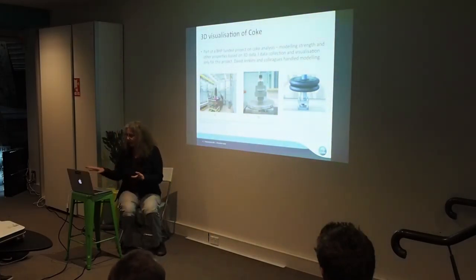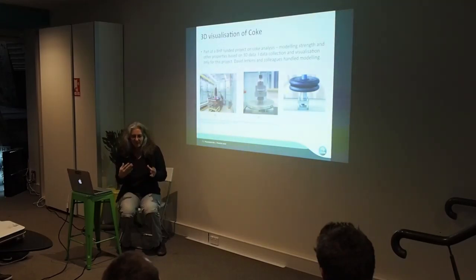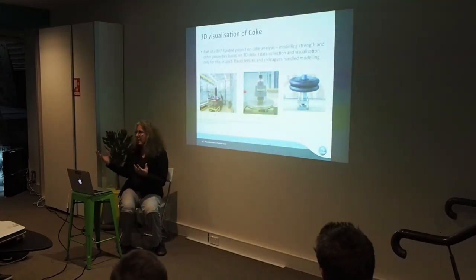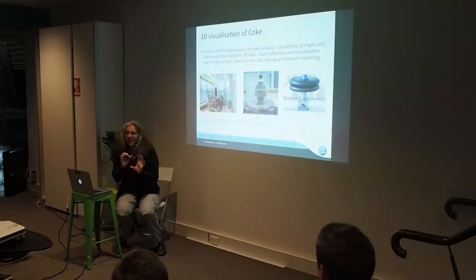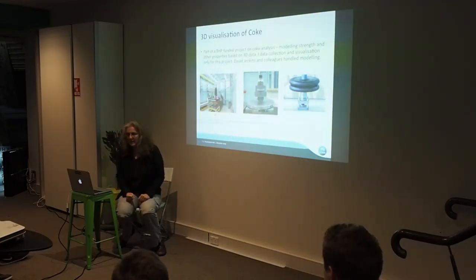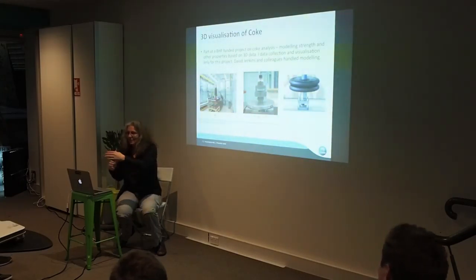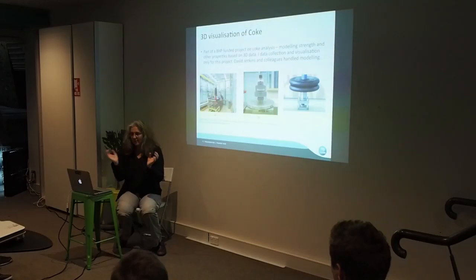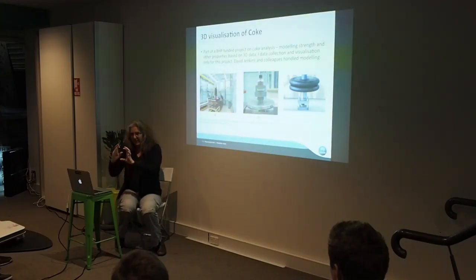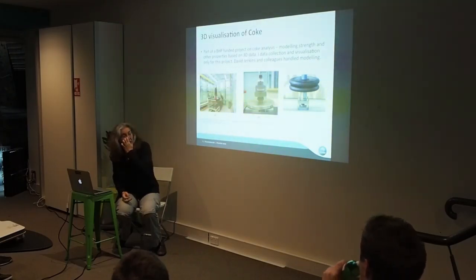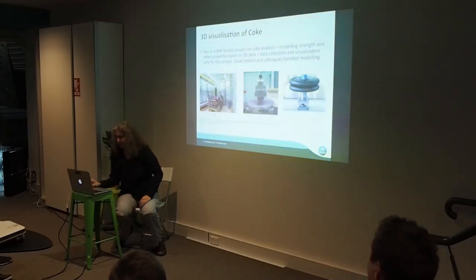I'll quickly go through a few applications we've done with the synchrotron. Some of the imaging I used to do was done in the lab — we have a lab X-ray source, almost a point source, five microns or so, or even smaller for a special model. But the synchrotron is different. It's a large facility with a particle accelerator that fires off X-rays at a tangent. It has a storage ring where electrons go around at the speed of light and spit off X-rays, which are collected in beam lines.